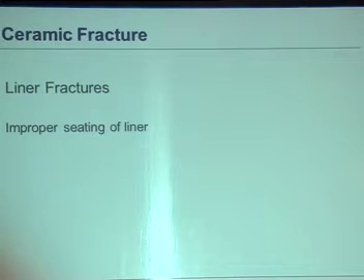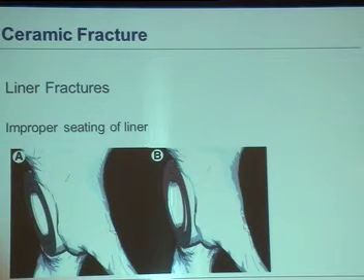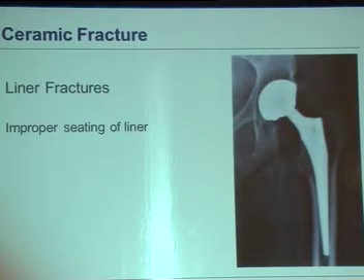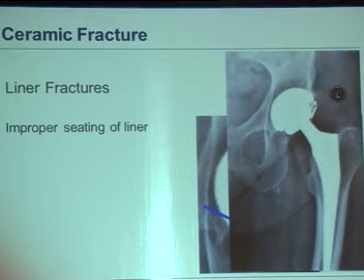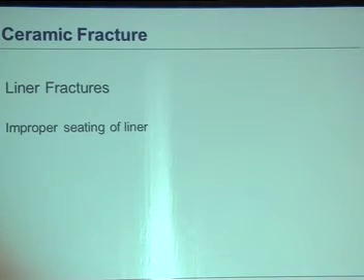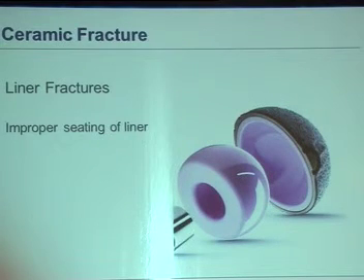One specific point regarding liner fractures is that improper seating of the liner plays a role as well. It's absolutely important that you check the full periphery of the cup and liner to make sure that it is properly seated. If there is slight elevation, it means there is point loading, which can lead to hoop stresses and fracture. In this particular x-ray, it might look great, but if you look, that area is already prominent. So that liner hadn't seated properly and it resulted in fracture later. Of course, these perhaps could potentially reduce those risks, but it is yet